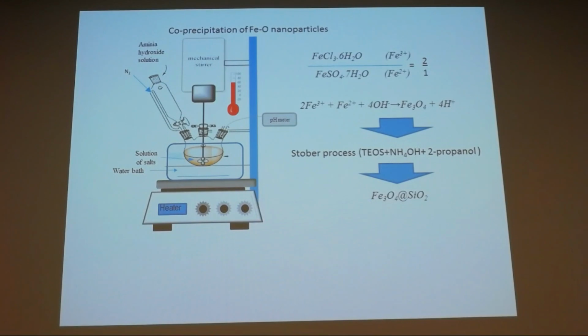So one of the methods which is at the moment very popular is to use magnetic nanoparticles in the fight with cancer, and for that some iron oxide nanoparticles are used, because those particles are actually allowed in the medical community to be introduced into the human system. So we have done co-precipitation of these nanoparticles from salts of this type, in the ratio 2:1. They are sources of iron-3 and iron-2 ions in this solution of salts. We added ammonium hydroxide dropwise, and the process was carried out in a nitrogen atmosphere at a temperature of 60 degrees centigrade.